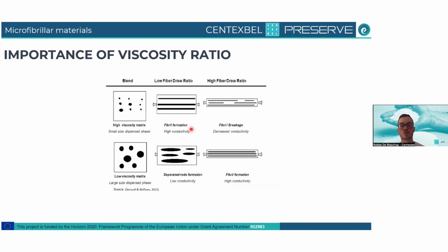And here I wanted to show you a graph of how this looks using different viscosities and also draw ratio, so how much you stretch the material during extrusion. We are using cast film extrusion, so we have a very low draw ratio, nothing compared to filament extrusion. But it is also notable that when you already create some fibrils that are pretty good during compounding, you don't have to stretch much,